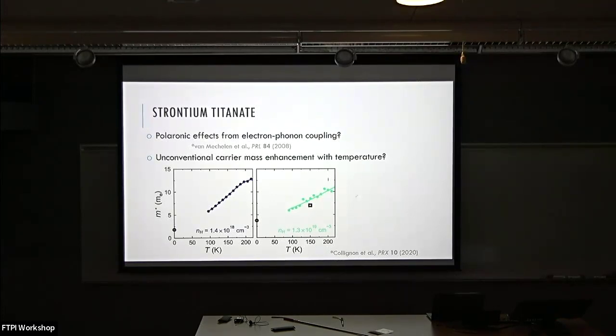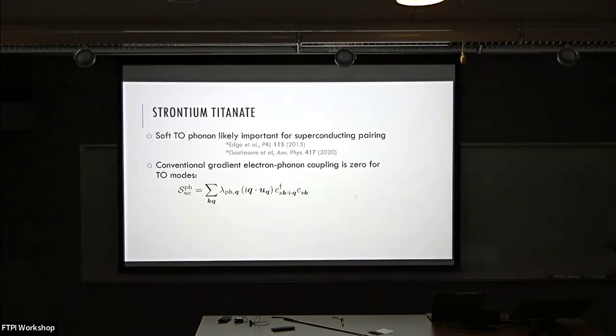What's happening? And then the second point that was also mentioned by Peter is, so if you have the soft TO-phonon that seems to be important for superconductivity and also for the normal state properties, the question is how you can couple to it. And now, of course, the conventional linear gradient coupling is identically 0 for a TO mode, since these two are equal. No, anyway, this is 0. So that means you need to find other ways to couple to it. So if this role is important, there has to be a way to couple.